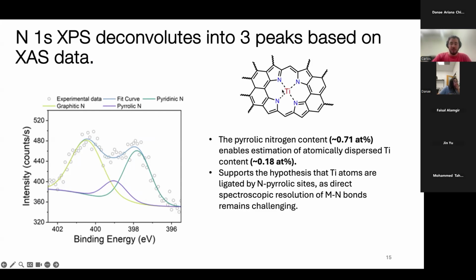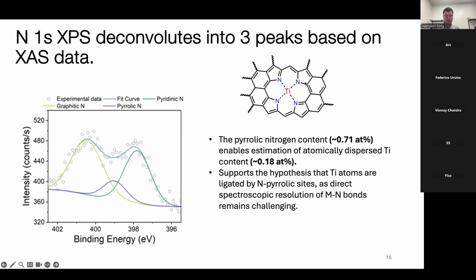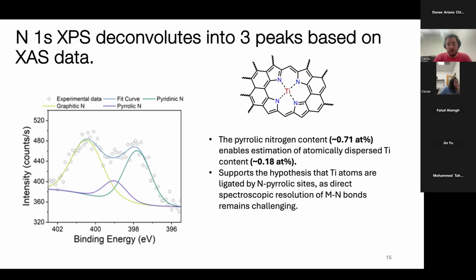And because we know that the structure has 4 nitrogens per each single titanium that we have, we estimate that the titanium content for these nanoparticles is about 0.18 atomic percent. And this also supports the hypothesis that the titanium is ligated to this pyrrolic nitrogen.